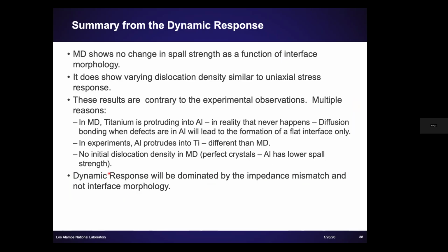The reason I show this slide, I don't have the coolest conclusions here, but I wanted to give you an example of work where we use molecular dynamics and experiments to try to design interfaces that can help improve mechanical response, both at low rates and also under shock in materials. But basically, the thing that ended up being interesting is that MD shows no change in spall strength as a function of interface morphology. It doesn't matter. It does show varying dislocation density, similar to uniaxial stress response. These are the opposite of what we see in experiments.